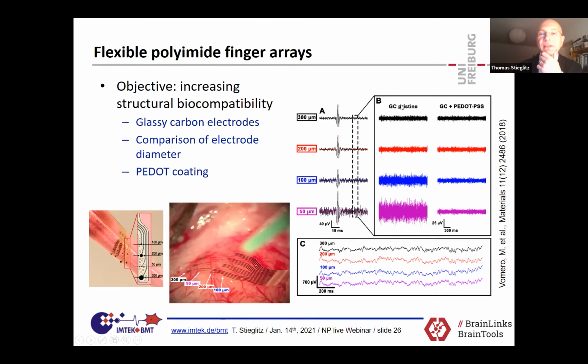What we've seen is that glassy carbon, GC here, is not that bad, but as expected, if you lower the electrode diameter, the noise gets higher and the signal to noise is not that good. However, if you coat these electrode surfaces with a polymer, PEDOT:PSS, one of those famous conductive polymers in neural implants, since this works more on the volume of the coating instead of the area of the cross-section, you get a good signal to noise, a low noise floor over all electrode diameters, being here on the surface of the brain. And these recordings are taken from a rat.